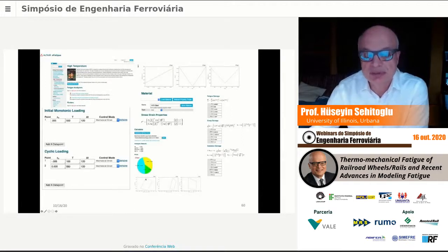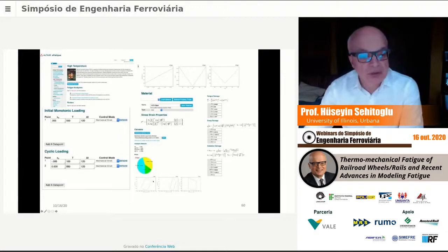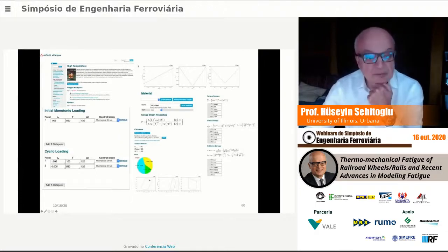So in this particular case, we are hot in tension. So this is an in-phase case, right? So the stresses are decreasing. This is the high temperature end of the cycle here, considerably. So this is stress versus mechanical strain, and it gives a fatigue life of about 544 cycles. So this is what's predicted from this.